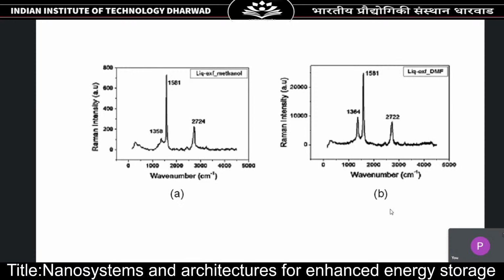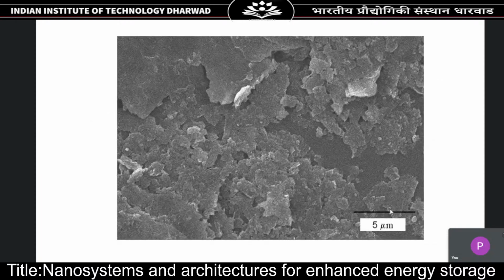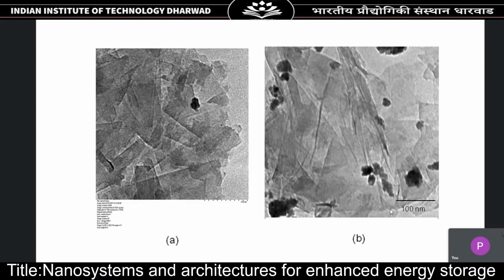These are the Raman spectra you can see on the left hand side and right hand side. The left hand side is with methanol as a solvent, and the right hand side is using DMF as a solvent. You can see the typical curves, the D band, the 2D band, and the G band. All these are seen in the Raman spectra. This is the SEM image of the exfoliated graphene. You can see that it is in the form of a layered structure.